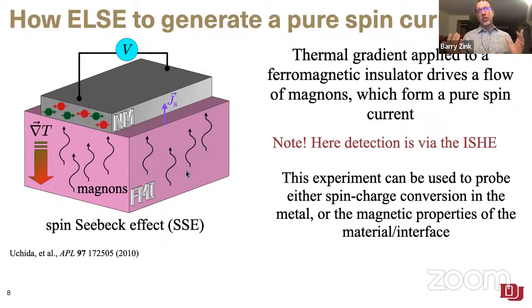We're thermally launching a flow of magnons that are a spin current at this interface. As they hit the interface, the inverse spin Hall effect converts that spin current, in this case maybe in platinum, into a charge current that we can measure. And so this is an important experiment now, and it allows you to both, as I will talk about in our experiments here in a minute, probe the spin charge conversion properties of different metals that you stick on top of, say, a relatively boring ferromagnetic insulator, if you want to think about it that way. You can also use it to study novel magnetic properties in the magnetic side of things, if you have an understanding of what's going on.